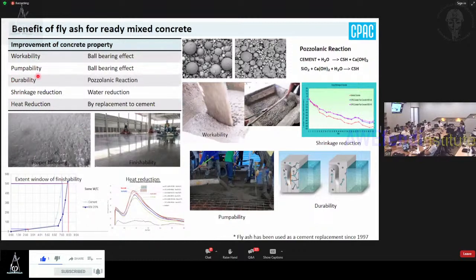The next one is about durability, because fly ash gives a pozzolanic reaction and gives more dense concrete in the future, with less strength loss. So this one is also very important for some kinds of severe environment. The next one: when we use fly ash in the concrete, you can reduce the water content, so you can reduce the shrinkage. Talking about drying shrinkage in the concrete, this is one thing that we always consider for floor type and large area casting. It's really helpful for this.